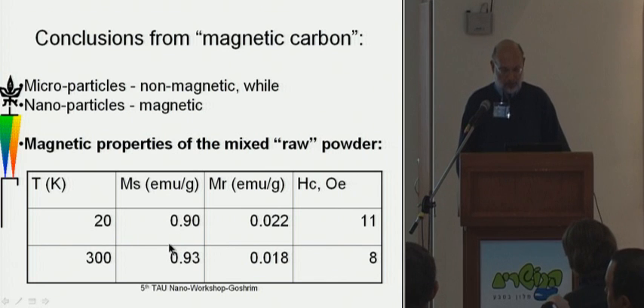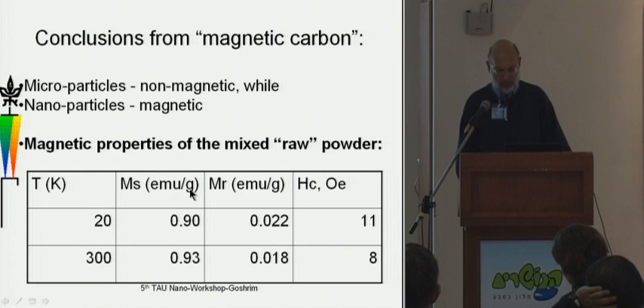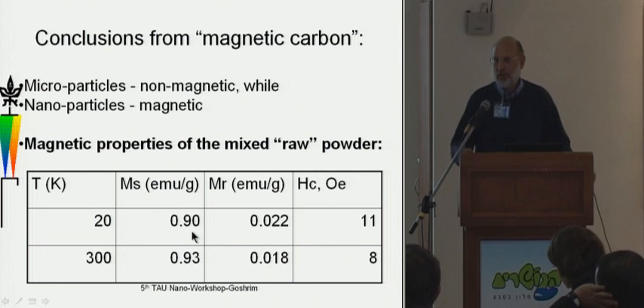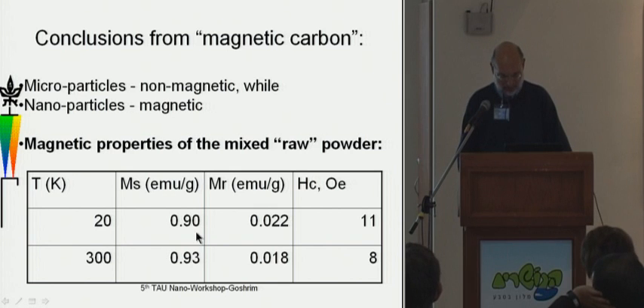We found that the residual magnetism is around 1 EMU per gram, and just for contrast, iron is about 200 EMU per gram. And this is in the raw powder. In other words, it's all still mixed. What we're trying to do now is collect enough of the pure magnetic particles to determine their characteristics.